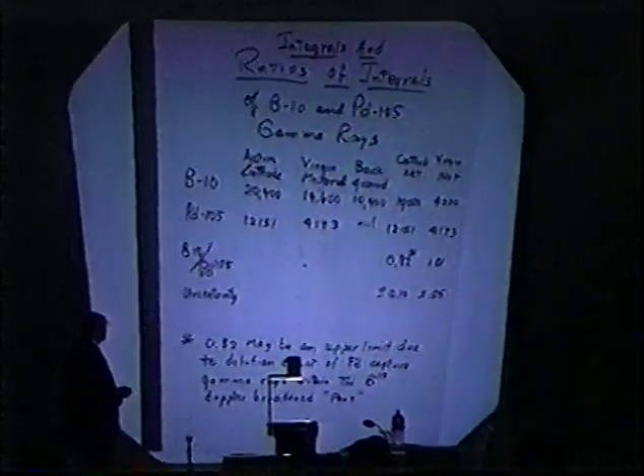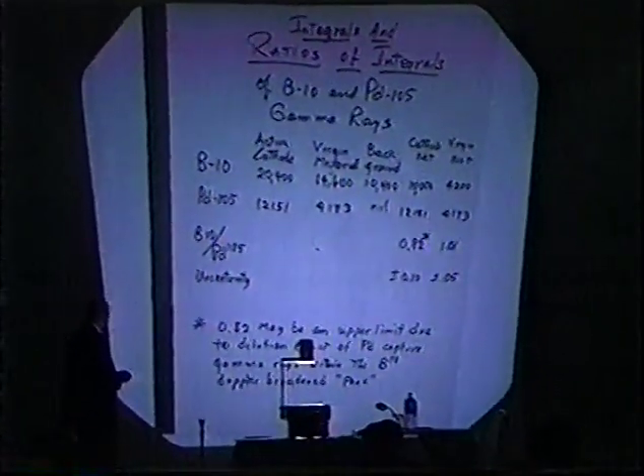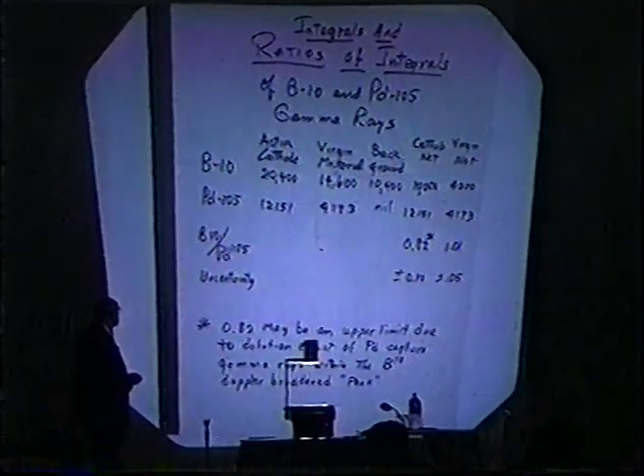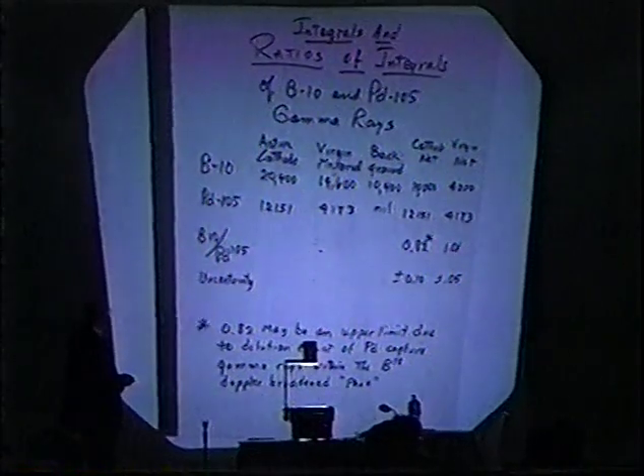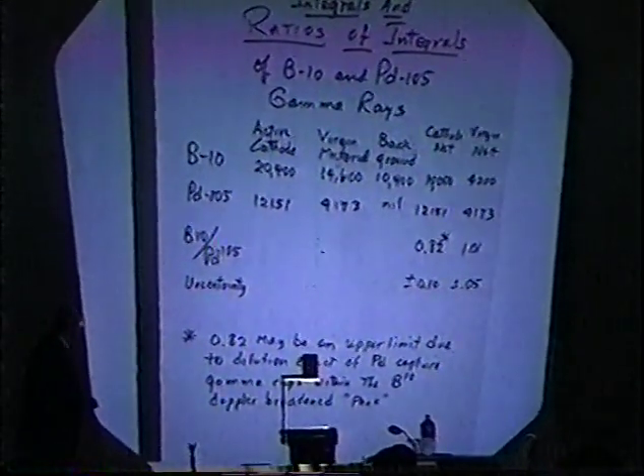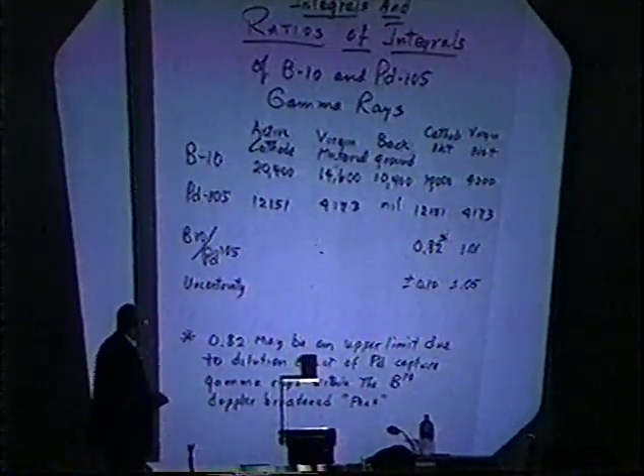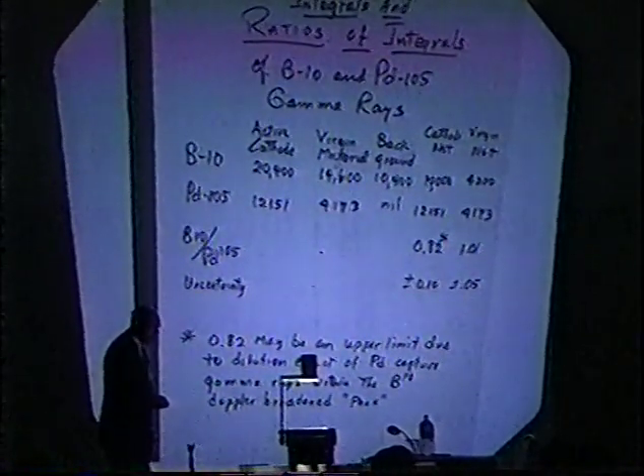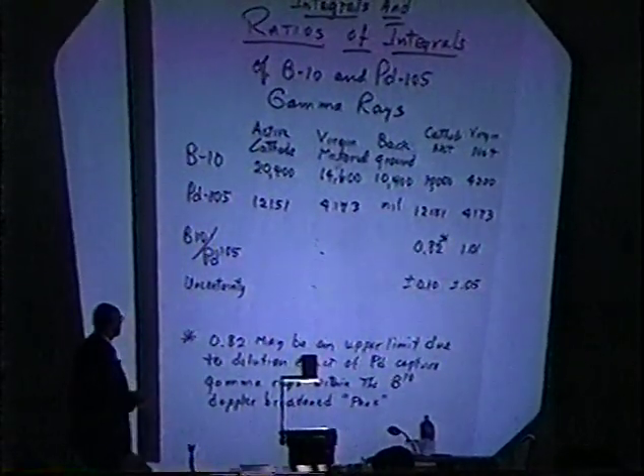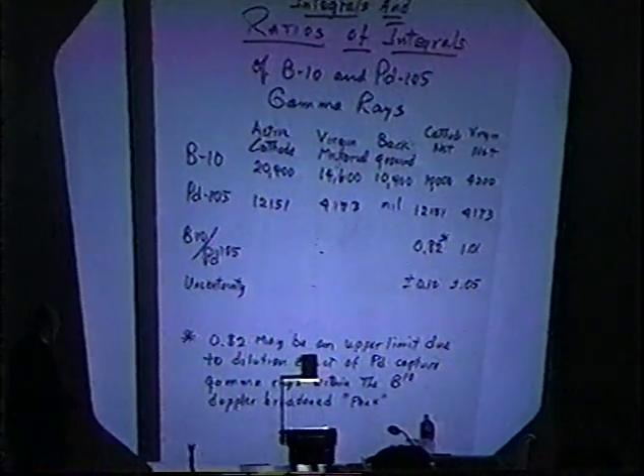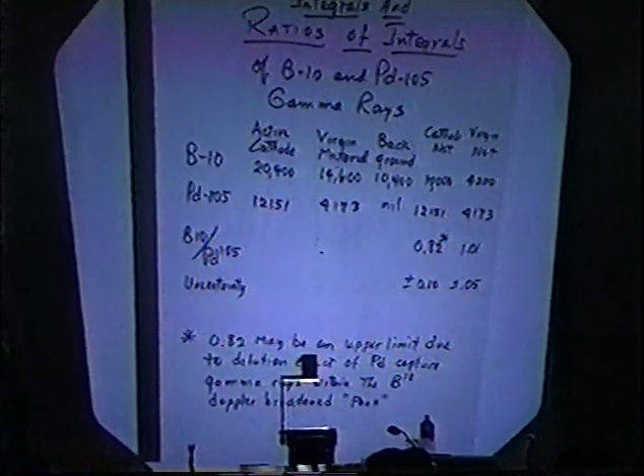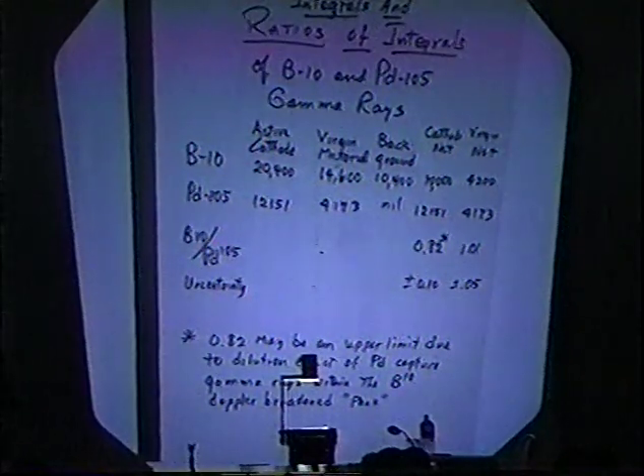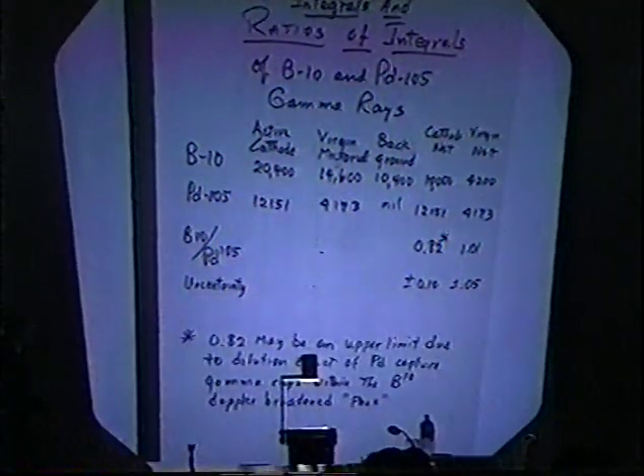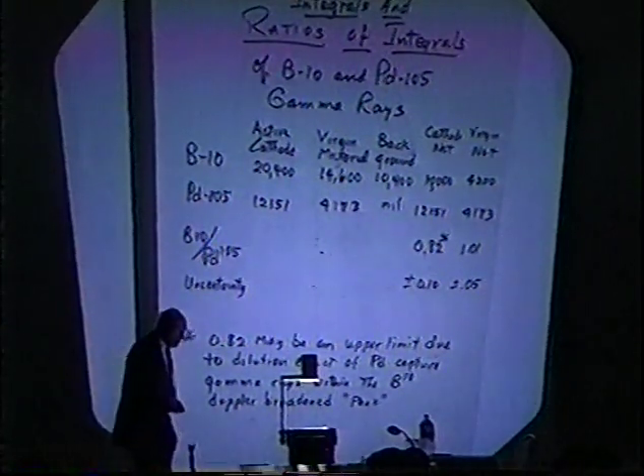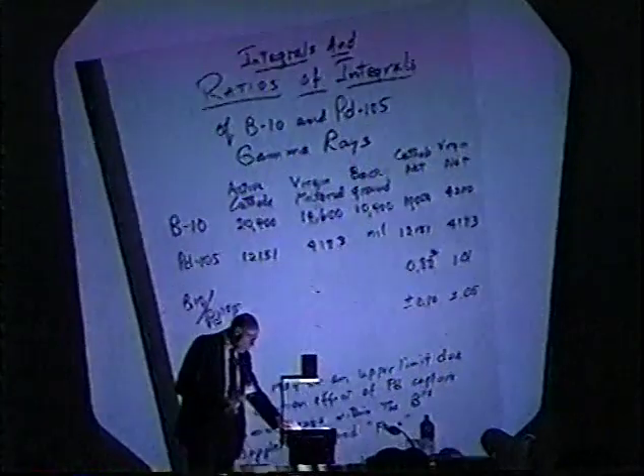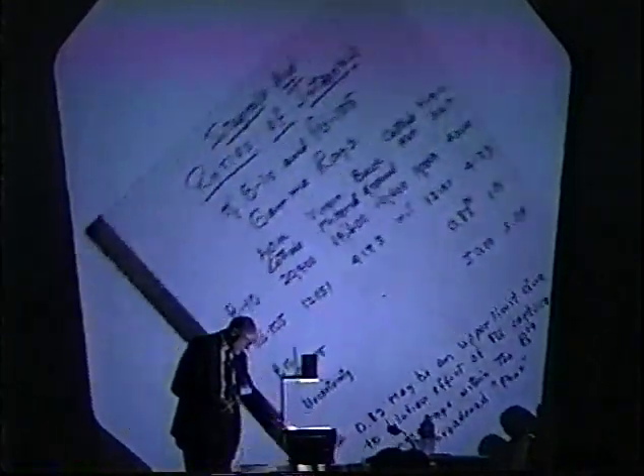So we do the ratios, cathode net of boron 10 to palladium 105, and you get a ratio of 0.82. And the net for the virgin is 1.01, or about an 18% drop. A burnout, you might say, of boron 10, or a loss of boron 10 relative to palladium 105. And the uncertainty, of course, is uncomfortably large, but nonetheless, I make a point down here that 0.82 may be an upper limit due to the dilution effect of a couple of palladium captured gamma rays within that boron 10 Doppler broadened peak, which I know are there from the literature. So, indeed, I think we have a suggestive, if not definitive, result.